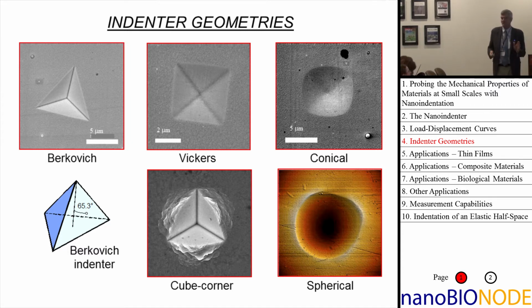Spherical indenters are very important, and I suspect in the bio world there's probably a lot of interest in using spheres because the spherical geometry is nice from a contact mechanics perspective. One of the nice things for spherical indenters in my world, in the hard materials world, is that because they are not singular, they're not pointy, then as you start to push this into the material, the stresses are finite to begin with, start at 0, and they build up as you push it in. And so you start off in the elastic regime in the material, and only later as you push this thing in further and further and further do you get to the plasticity. So you can actually use that to probe the transition from elasticity to plasticity.